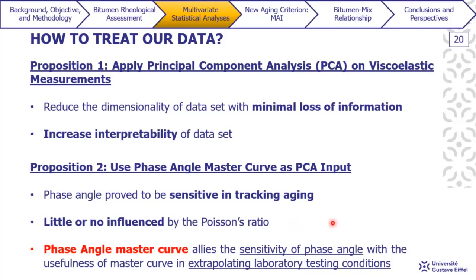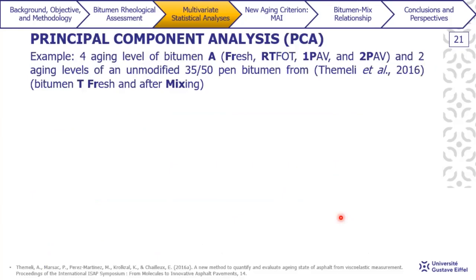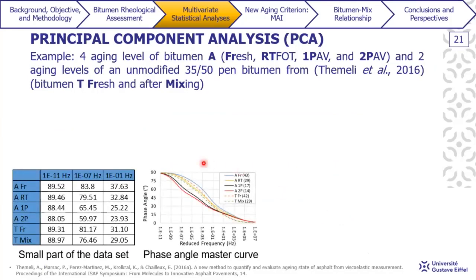So in this case, the powerfulness of the phase angle master curve seems to be interesting since it combines the high sensitivity of phase angle with the usefulness of master curve in extrapolating laboratory testing conditions. So here I'm gonna show an example. I used the 4 aging levels of bitumen A that I presented previously.